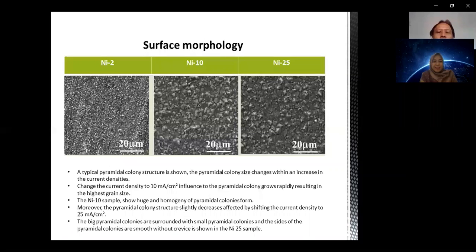We can see the surface morphology of the 3 samples. A typical pyramidal colony structure is shown. The pyramidal colony size changes as the current density increases. Changing the current density to 10 milliamps per centimeter squared makes the pyramidal colony grow rapidly, resulting in the highest grain size. The nickel 10 sample shows a huge and homogeneous pyramidal colony. Moreover, the pyramidal colony structure slightly decreases when the current density is shifted to 25 milliamps. The big pyramidal colonies are surrounded by small pyramidal colonies, and the sides of the pyramidal colonies are smooth without crevices in the nickel 25 sample.